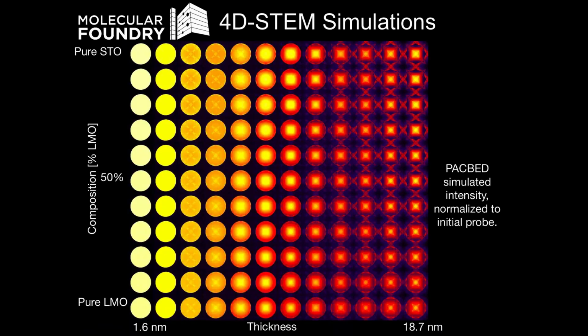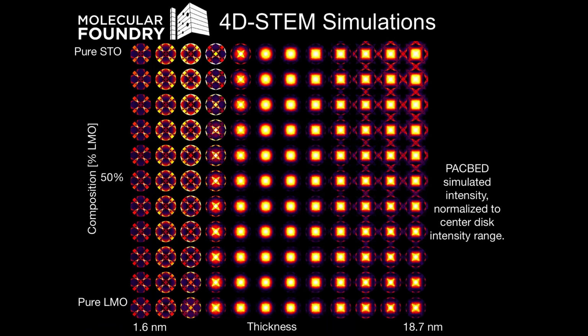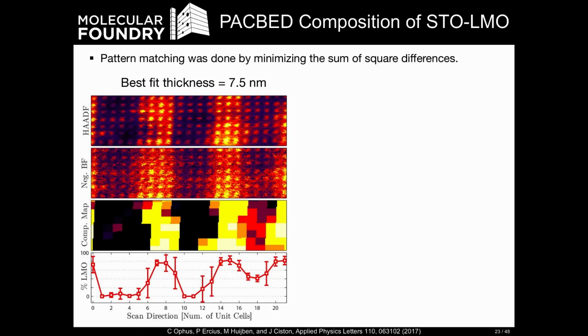If I just increase the contrast here, you can see there's a really strong dependence on thickness and a somewhat weaker dependence on the composition. This is just the center disk position. For each one of those previous experimental CBED images, PACBED images, I can match it to this simulation, and that's what this one looks like here. For this data set, the best fit overall thickness was 7.5 nanometers. The composition map below shows that we can pick up this multilayer stack geometry as you alternate between STO and LMO composition.